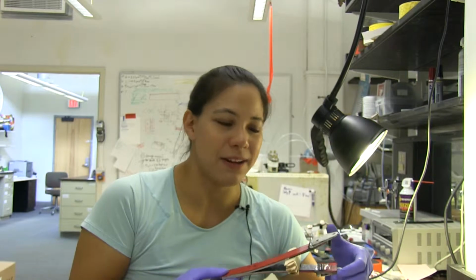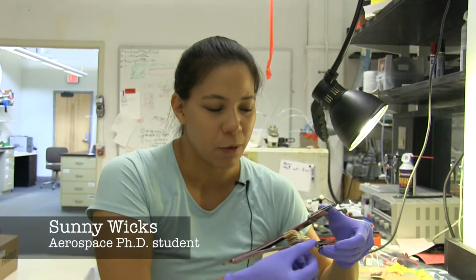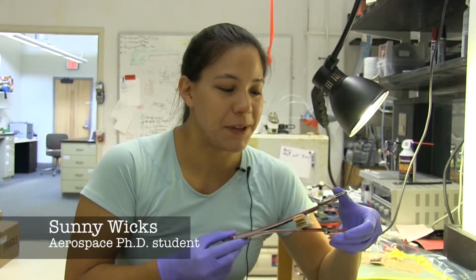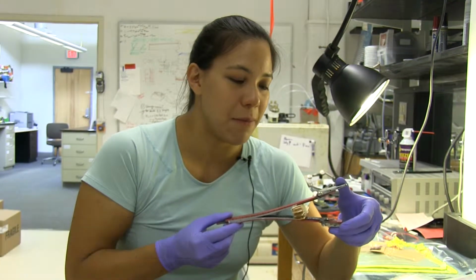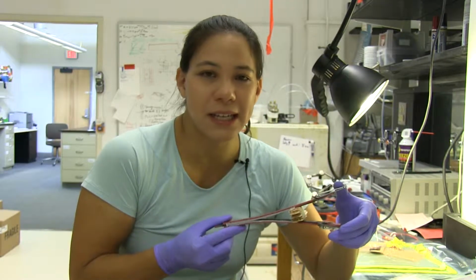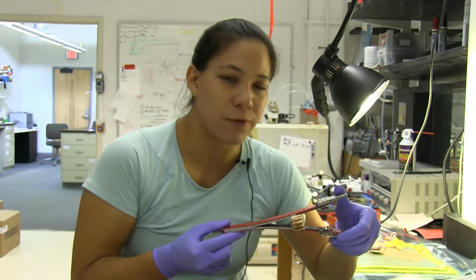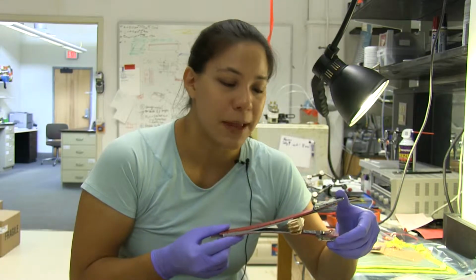The nanotubes I've added are throughout my entire laminate. They are in the black part of the composite, which is between these red plates. The nanotubes add very little weight, and we're looking to see how the minute addition of a small amount of CNTs can drastically change the performance of a composite by reinforcing against fracture and improve the toughness.